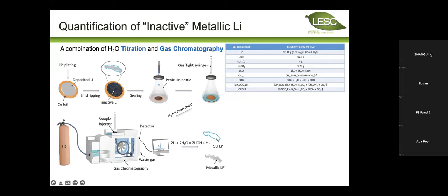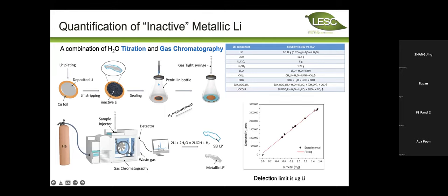If we use water, by the way, you don't have to use water. There's many other choices of solvents, depending on what you want to study. In this case, we want to study the water lithium reactions to quantify the amount of dead lithium. The calibration curve is very, very accurate. We can get up to 1 microgram lithium metal accuracies.